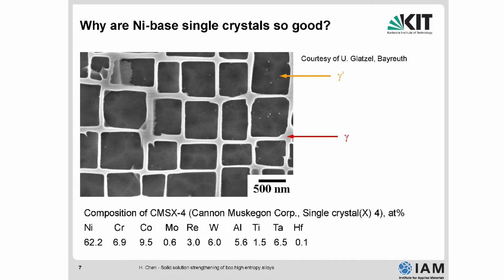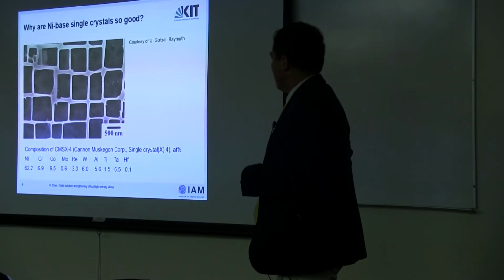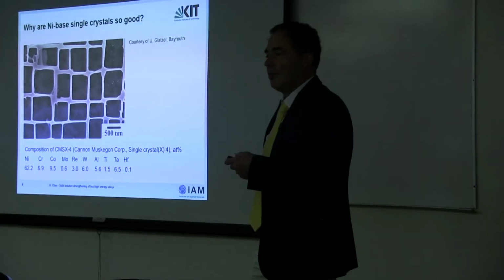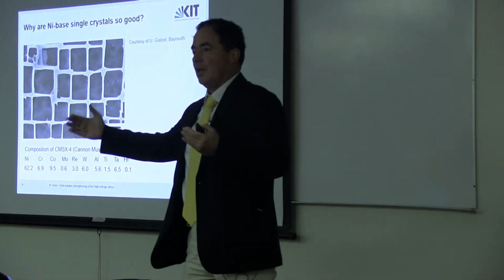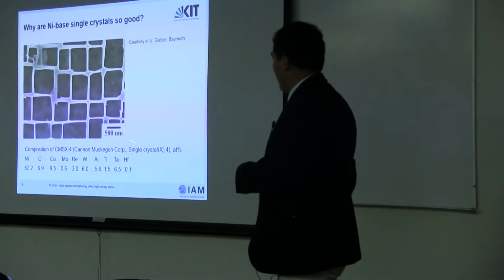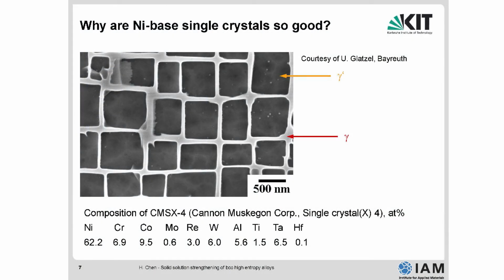This is the micrograph, a TEM, transmission electron micrograph of a nickel-based single crystalline alloy which is called CMSX4. CMSX4 stands for Cannon Muskegon Corporation Single Crystal number 4. Number 4 because they developed a series of alloy compositions, and some of them were successful, some of them were not successful. Obviously, the number 4 alloy with this chemical composition was extremely successful because it now represents the state-of-the-art material in the hottest section of an aero engine.